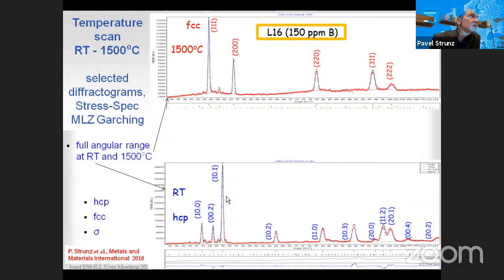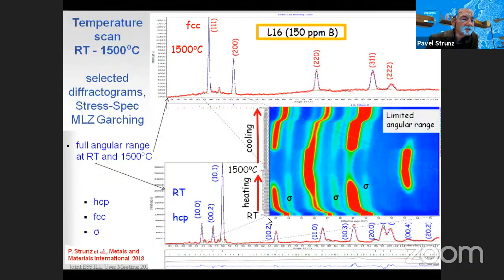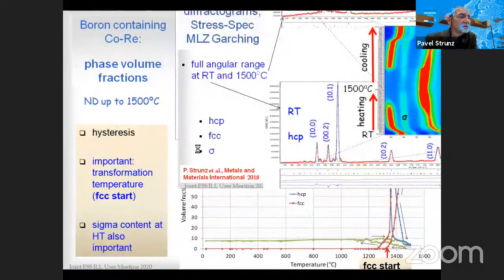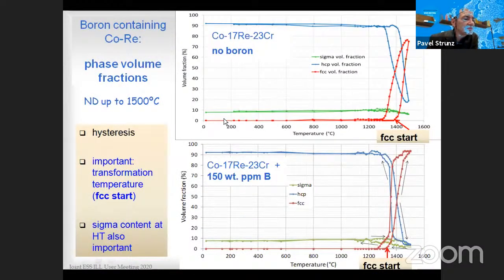So we measured this at Garching at the Stress-Spec machine in the temperature range from room temperature to 1500 degrees centigrade. At room temperature, the diffractogram shows hexagonal phase with some sigma phase in between. At high temperatures, 1500 degrees centigrade, there is only FCC phase with some sigma phase still visible. And we can also determine the structure in between, in some limited angular range, but sufficient to see hexagonal peaks, FCC peaks, and sigma peaks. When we evaluate this for all our boron-containing samples, we can see the evolution of the fractions of HCP, FCC, and also sigma phase. And the most important is that for all boron contents we are able to determine this FCC start temperature.